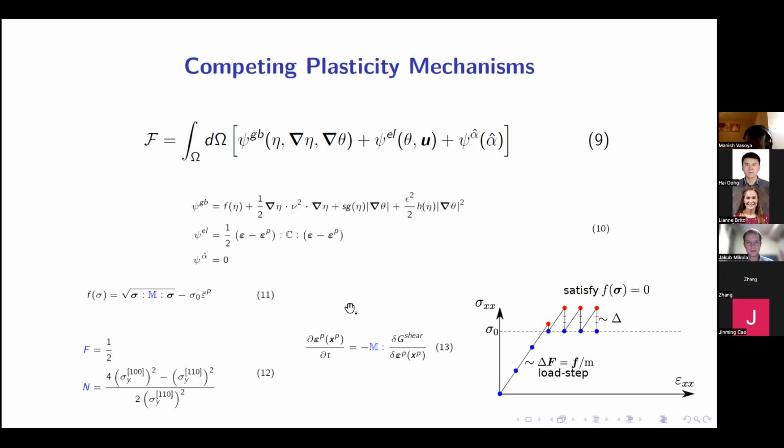As a first order approximation, we didn't really go into crystal plasticity. That would probably be the best plasticity model dealing with single crystals, but we wanted to have something simpler. So we decided to use Hill yield homogenized plasticity, which is easier to implement, but there is still some anisotropy that could provide us some insights into how these systems are evolving.